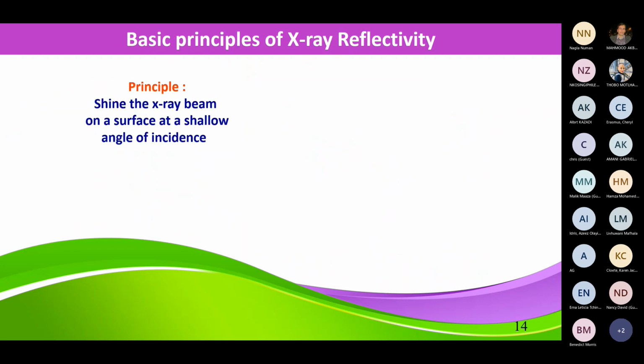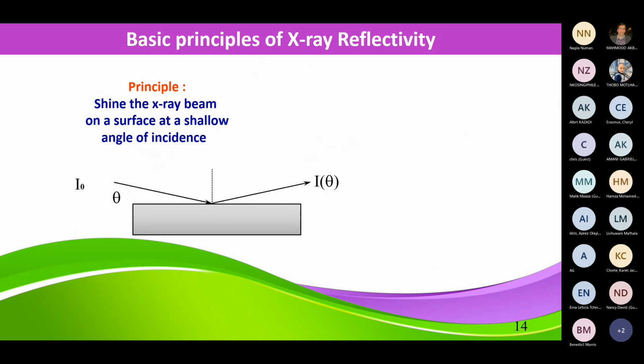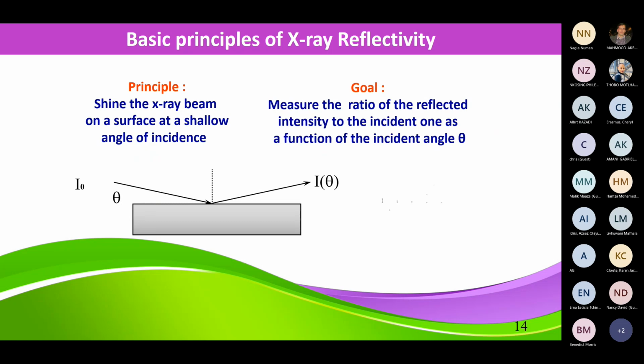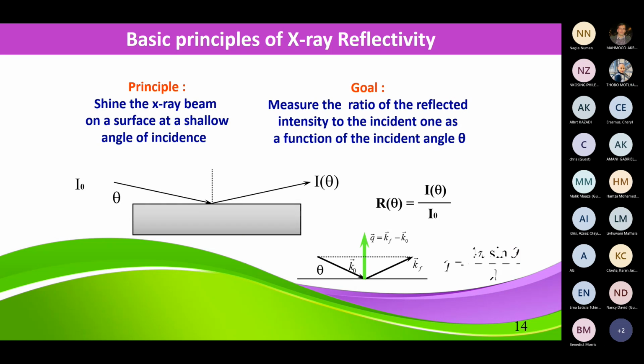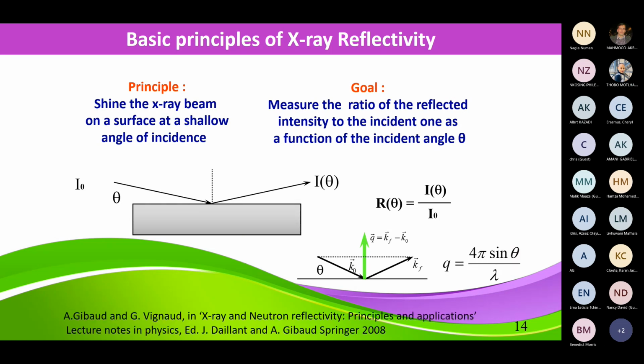Just to give you an insight of what reflectivity is, you shine the X-ray beam at a very shallow angle, you measure the reflected intensity, and the reflectivity is just the reflected intensity divided by the incident one. So this is something which is always less than 1. It's 1 if you totally reflect the beam, and then it goes down, and you can totally reflect the beam at low angle.